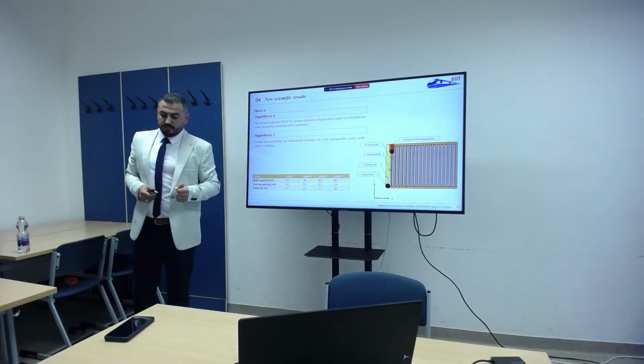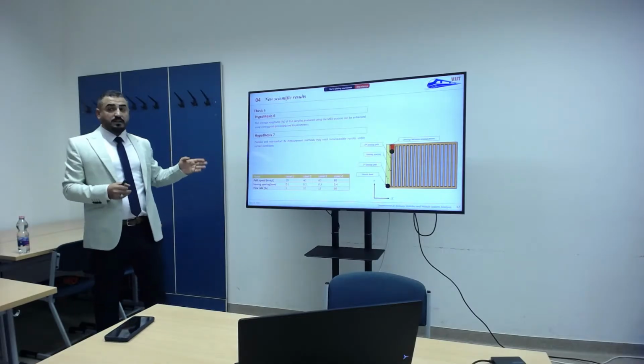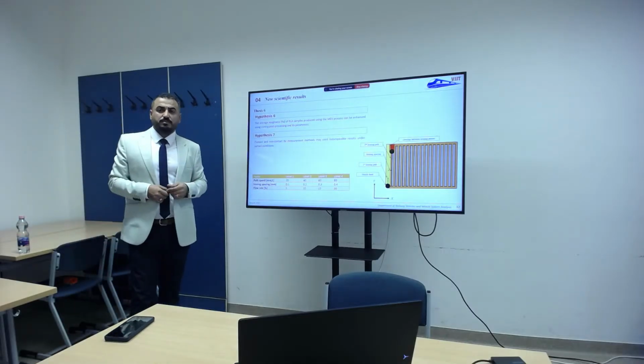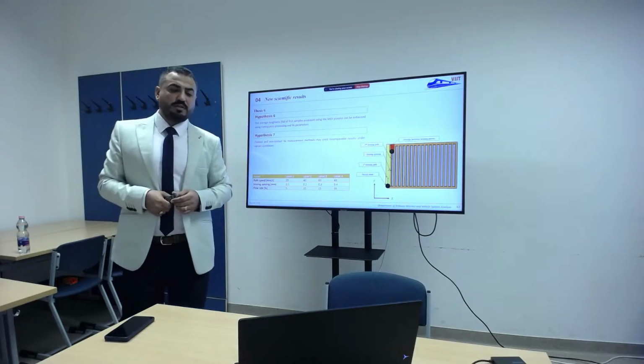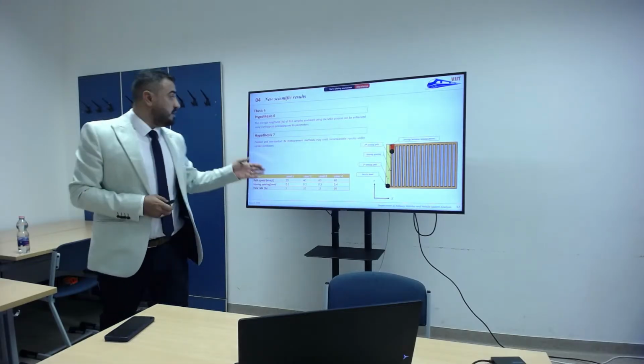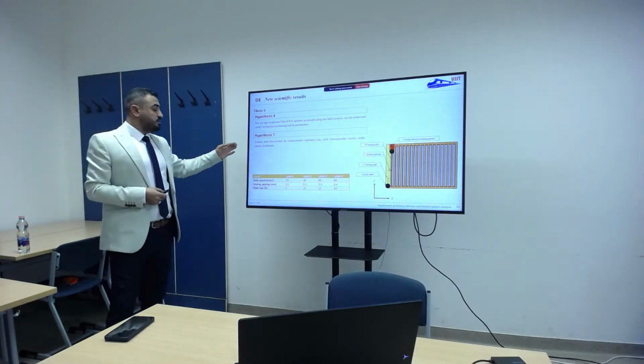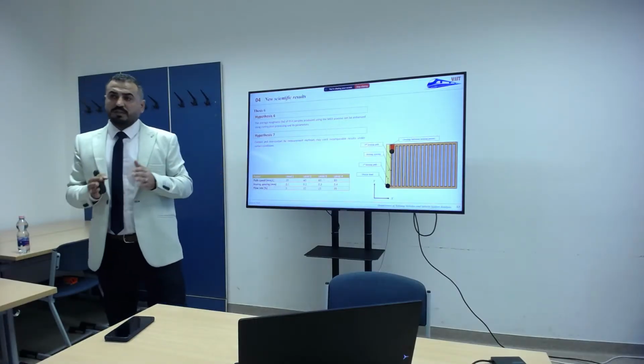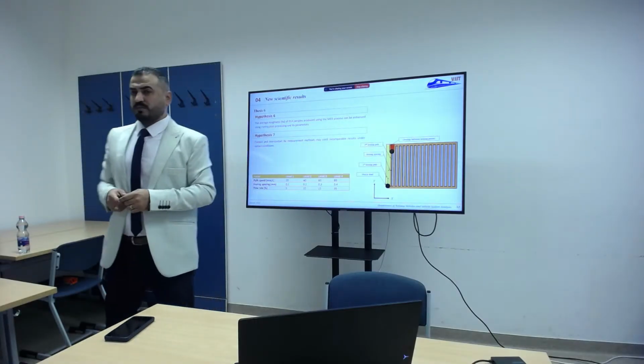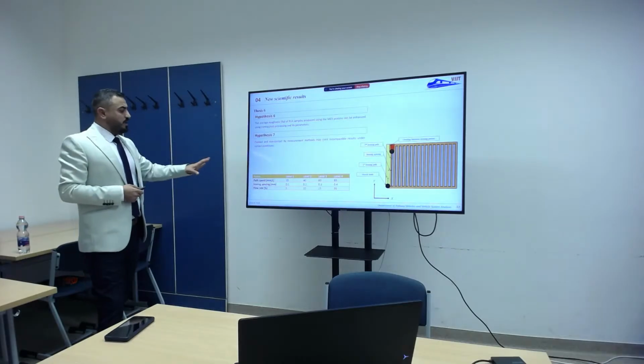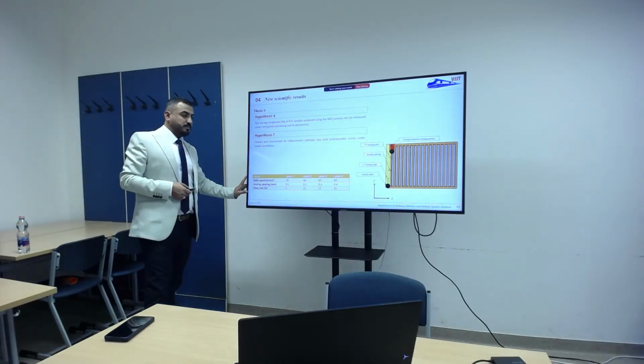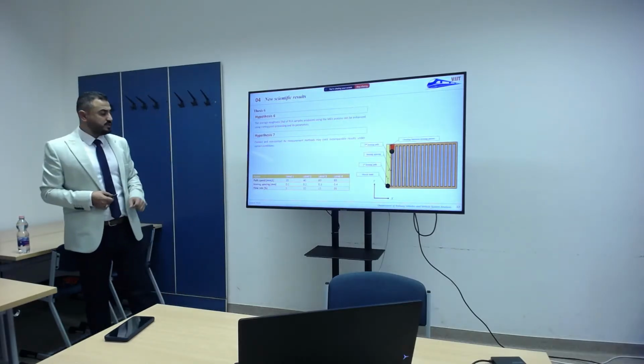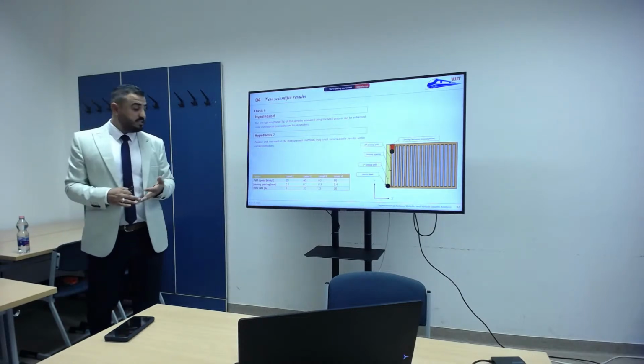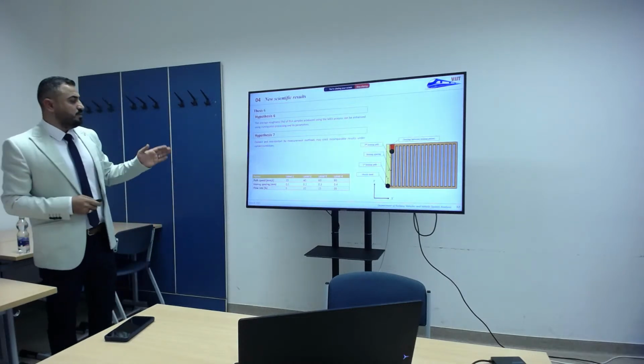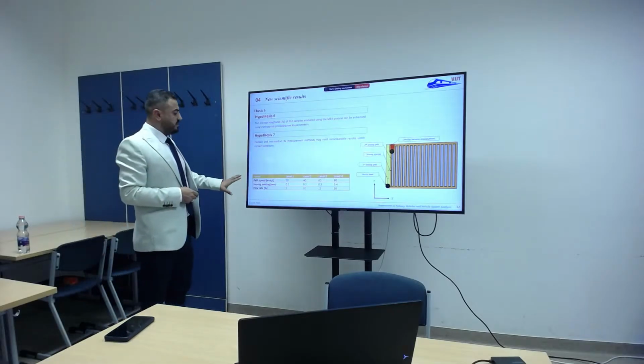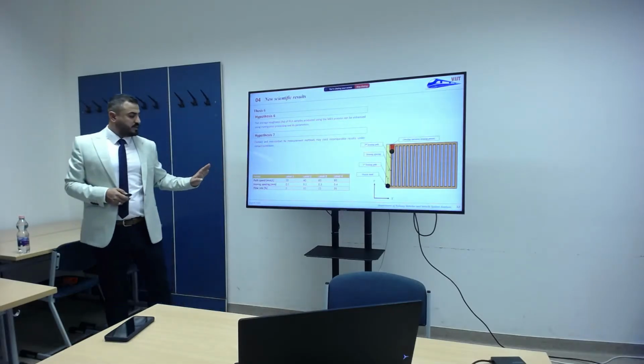In this thesis point, I investigated the effect of ironing post-processing on the value of average roughness. I also studied the difference between the contact measurement method and the non-contact measurement method. So I studied three parameters for the ironing post-processing: bed speed, ironing spacing, and flow rate, with four different levels, and I studied every parameter independently.